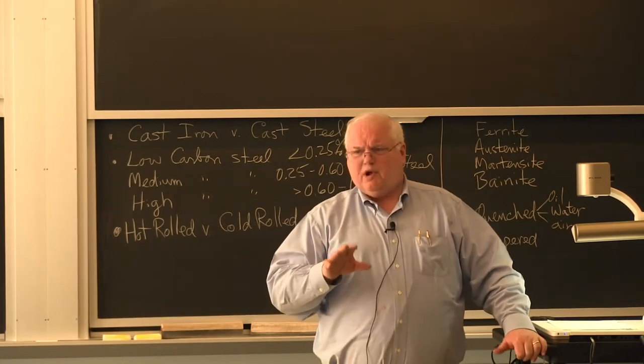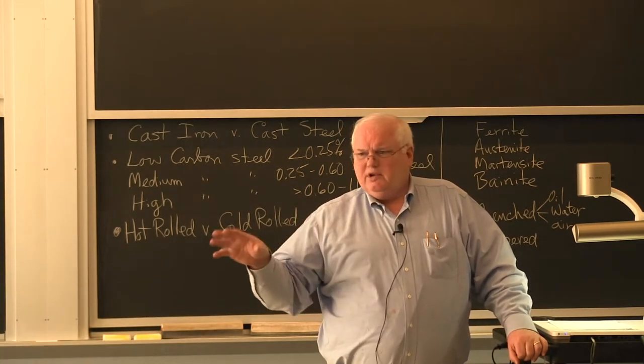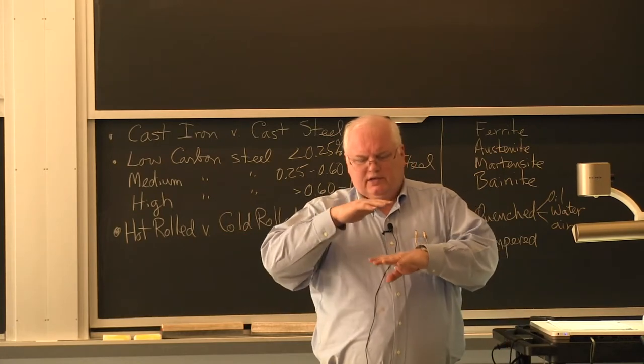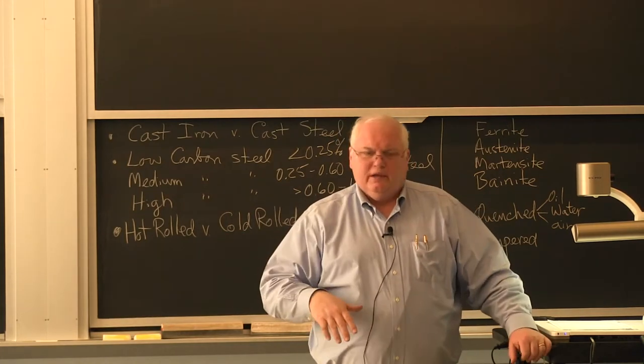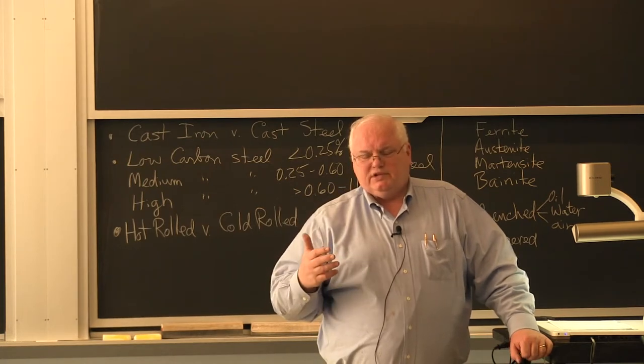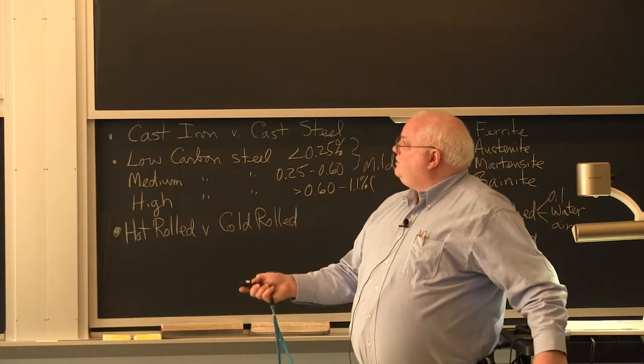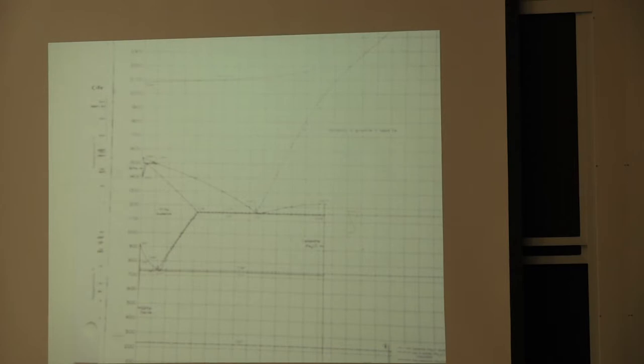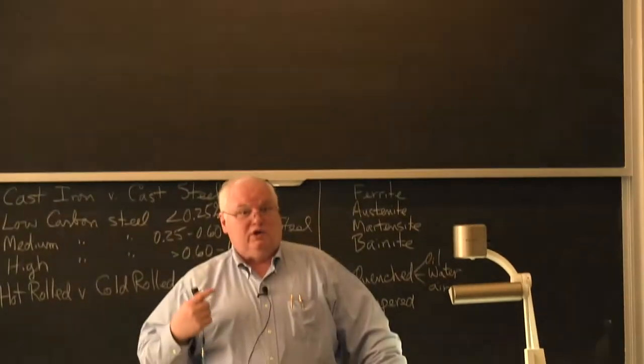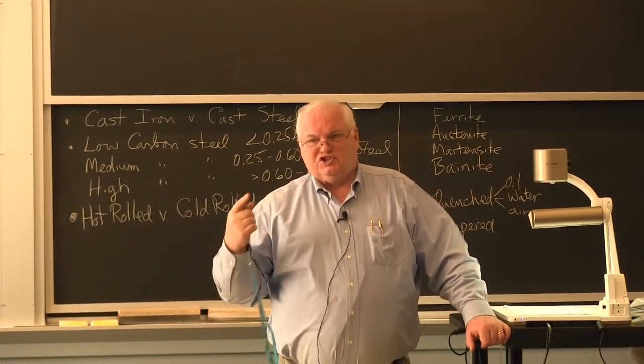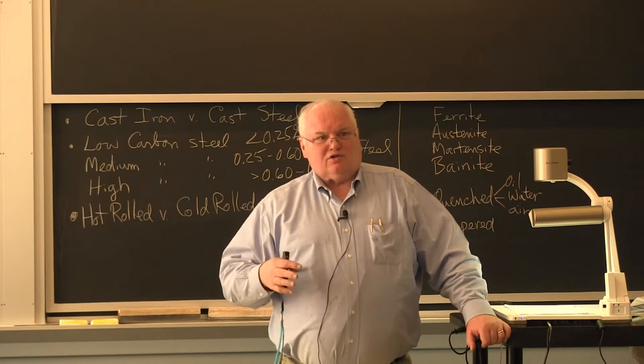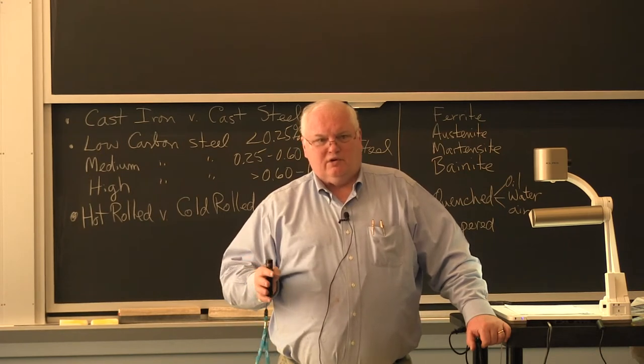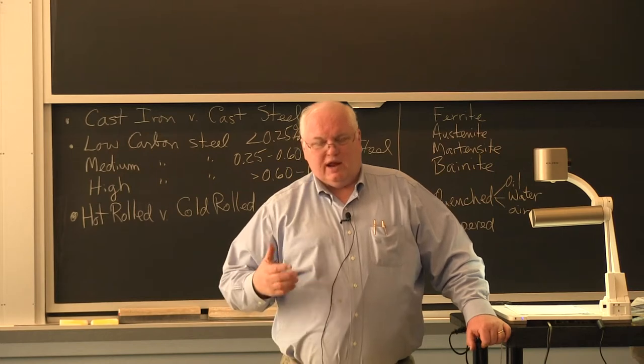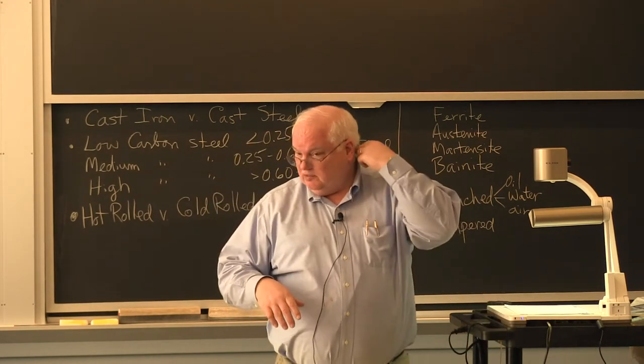steel mills are fairly expensive propositions. A hot rolling mill is about a $1 billion facility, and you take these slabs, you put them in a furnace, you get them up to about 1100 degrees centigrade, okay? So 1100 centigrade is up in this region, and you just put them through at 1100 centigrade, 1200 centigrade, the stuff rolls like butter. Now the steel rolls that are rolling this are cold, and they're rolling hot material, so you have to be careful about how you handle things, and you may water cool the rolls so they don't get too hot and things like that.